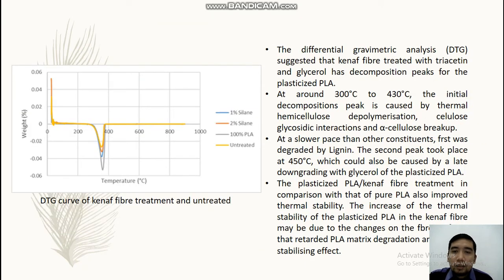Okay, for this DTG curve, okay, suggesting the Kenaf fiber treated with silane and glycerol has a decomposition peak for the plastic PLA at around 300 to 430. The initial decomposition peak is caused by thermal hemicellulose depolymerization, cellulose glycosidic linkage, and cellulose breakup at a slower pace than other components, was first degraded by lignin. The second peak took place at 450, which could also be caused by a late downgrading with glycerol of the PLA.